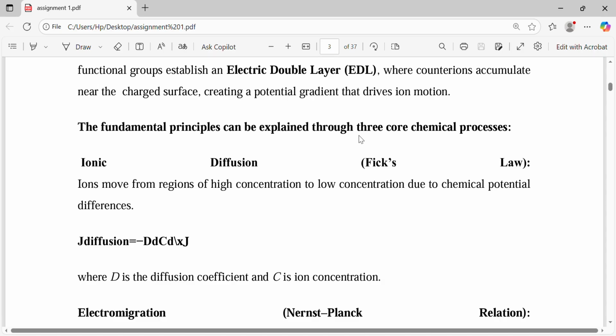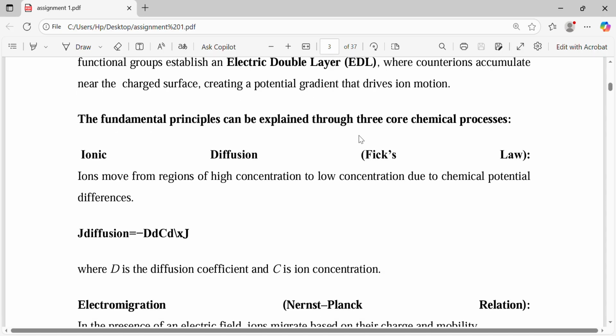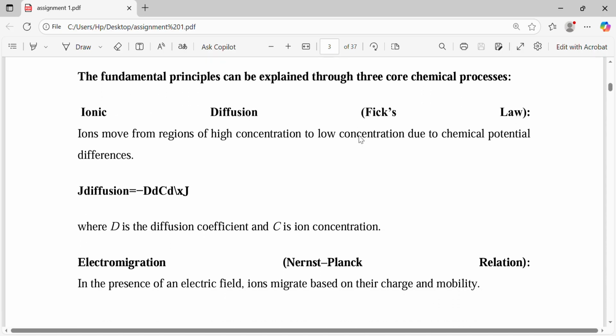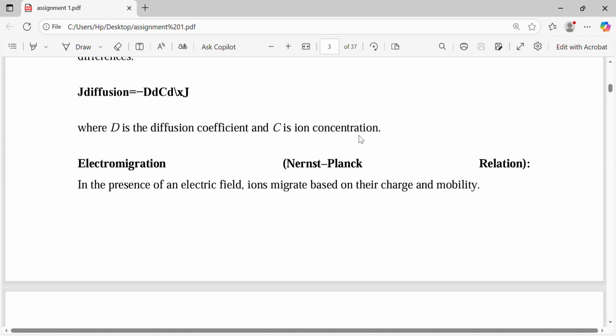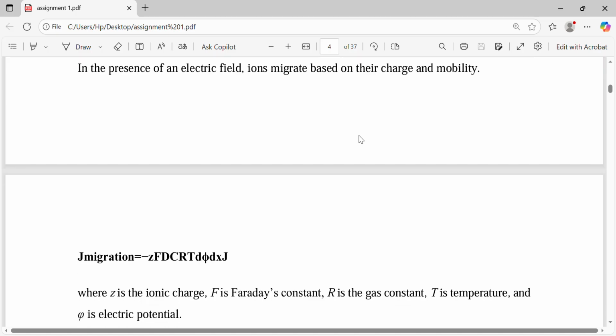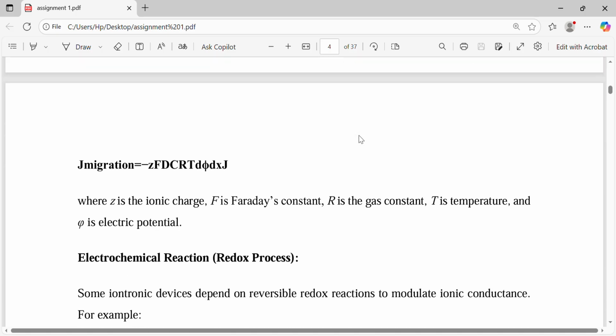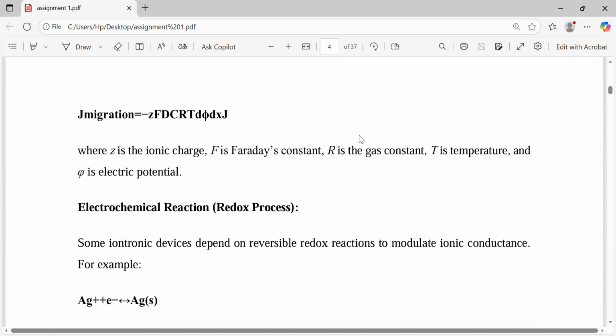First, ionic diffusion, Fick's law: ions move from regions of high concentration to low concentration due to chemical potential differences. J_diffusion is equal to minus D dC/dx, where D is the diffusion coefficient and C is the ionic concentration. Next, electromigration, Nernst-Planck relation. In the presence of an electric field, ions migrate based on their charge and mobility. J_migration is equal to minus z F D C / (R T) dφ/dx, where z is the ionic charge, F is Faraday's constant, R is the gas constant, T is temperature, and φ is electric potential.